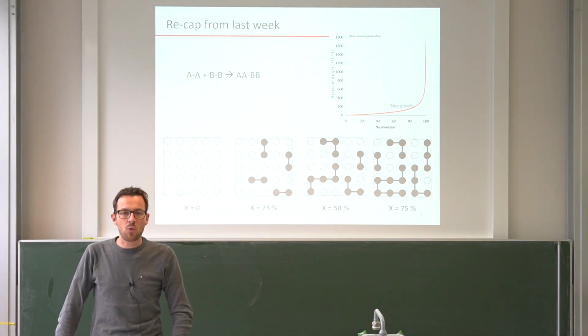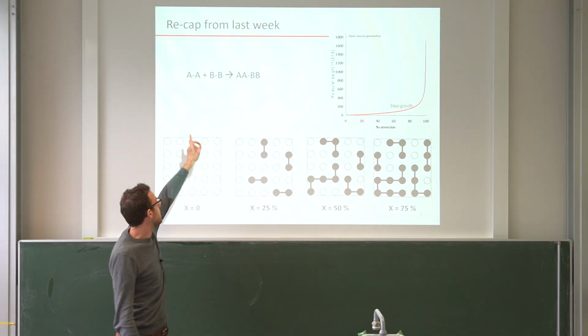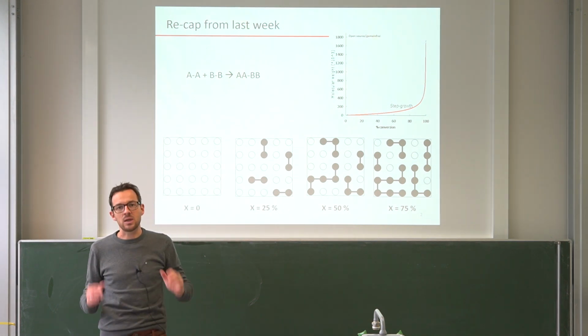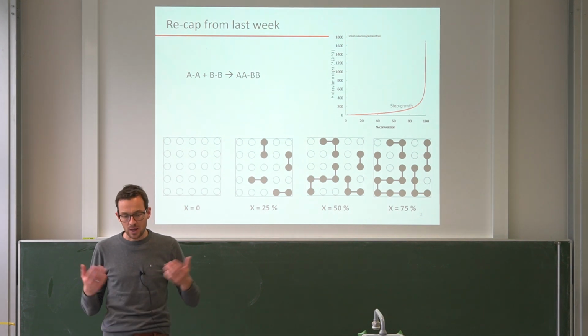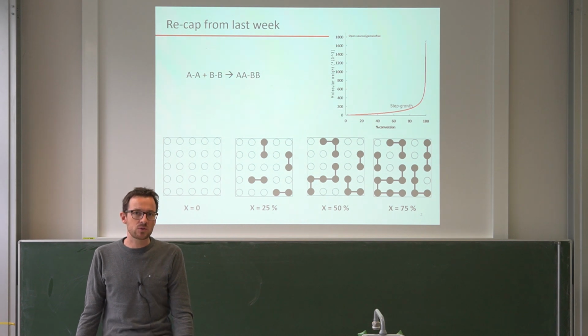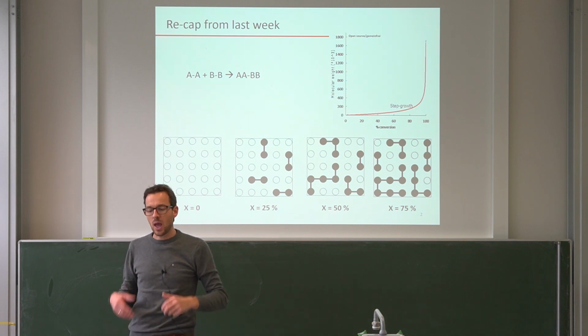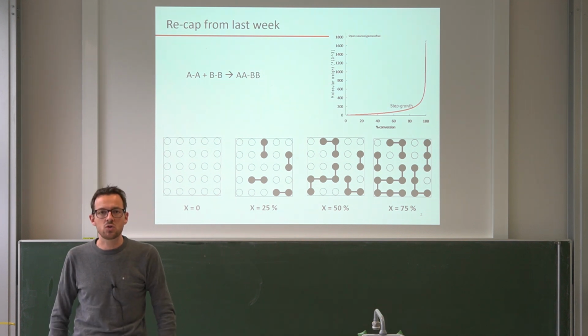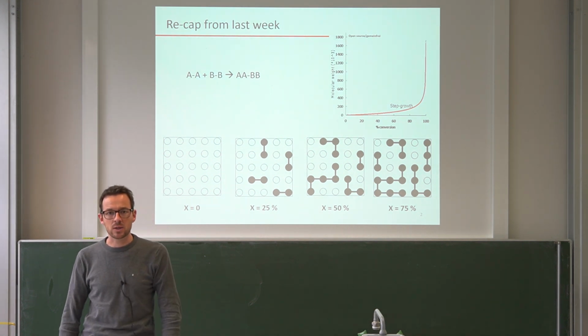And the second very important consideration we looked into was the effect of stoichiometry. And there we found that it's really essential that A and B are present in equal amounts in the reaction. If this is not the case, then we will never get large polymer chains. Now this of course seems like disadvantages, but we also discussed that the big advantage of this reaction type is that we have the functional groups straight in the backbone of the polymer. And this allows us to tailor the affinity of individual polymer chains, and that makes very high performing, durable materials.